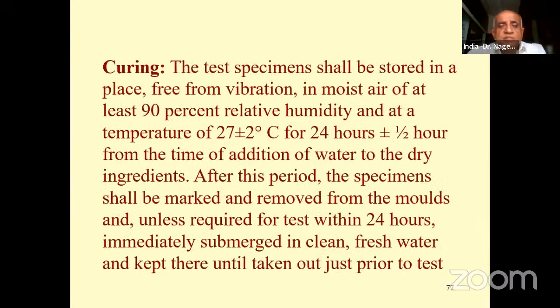Then where do you keep the specimen after 24 hours? Again, maintaining the cube for the first 24 hours is also equally important, because it should not lose water from the concrete cube that is cast. So the test specimen shall be stored in a place free from vibration, in moist air of at least 90% relative humidity, and at a temperature of 27 plus or minus 2 degrees Celsius for 24 hours.